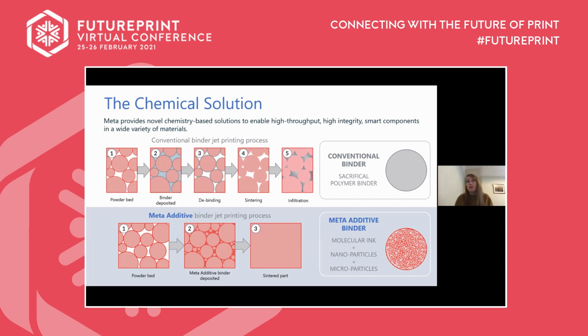And held within that molecular component, you also have nanoparticles and micron particles. And they help fill in some of the interstices or the pores of the powder bed. The nanoparticles also help to lower the processes which you need to do a heat treatment step after. So there's no debind step. You can shorten some of the processing times. But on the next slide, let's have a look at some of the other benefits to the Meta technology.